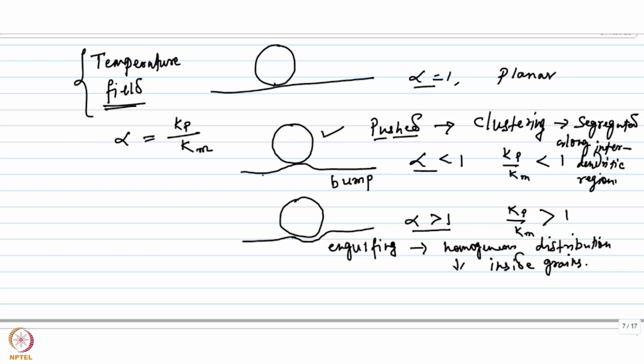So the particles will tend to roll down over this bump, and this will lead to pushing of the particles, which will in turn lead to clustering. On the other hand, when alpha is greater than 1, a trough is developed near the particle, and the interface can now engulf the particle, leading to uniform distribution inside the grains.